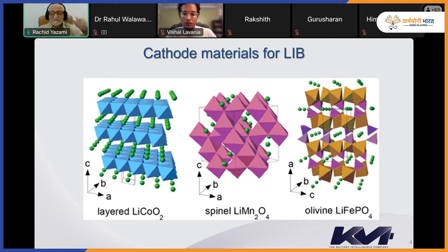But this battery, the spinel usually has a higher voltage than the layered structure, the lithium metal oxide. So this one, the lithium manganese spinel, the voltage can be as high as 4.5 volt, whereas the lithium metal oxide, the layered structure, the voltage at the end of charge is 4.2, 4.3 volt.